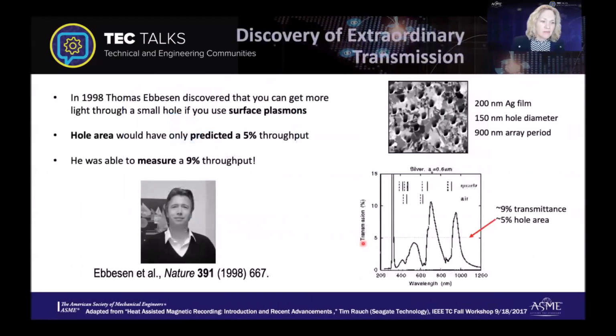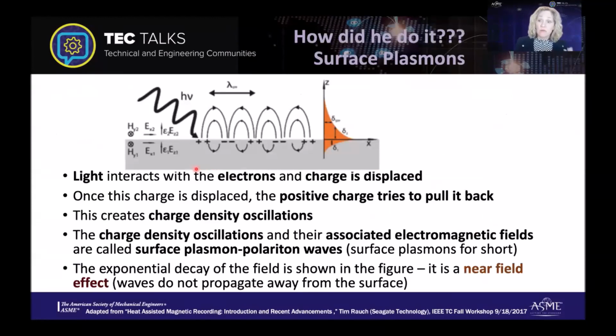So in 1998, Thomas Ebbesen actually discovered you could get more transmission than what would normally come through an aperture with surface plasmons. He had a silver film with 150 nanometer holes in it. The hole area would have predicted about a 5% throughput, but he was actually able to almost double that with a 9% throughput. And so how did he do that? He did that with surface plasmons.